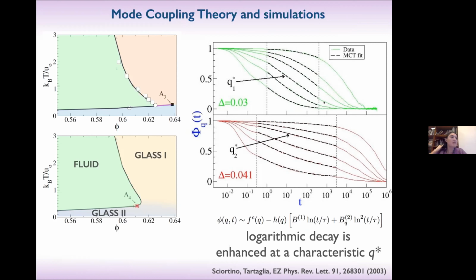And so there will be a characteristic Q vector, Q star, at which the logarithmic relaxation is enhanced. So if you're looking for the higher order singularity, typical anomalous dynamics, when you look in the density correlator, there will be a selected Q that will be a characteristic length that is important in your arrest mechanism, at which the logarithmic behavior is enhanced. So this was for the A3 point. We are very far from it.